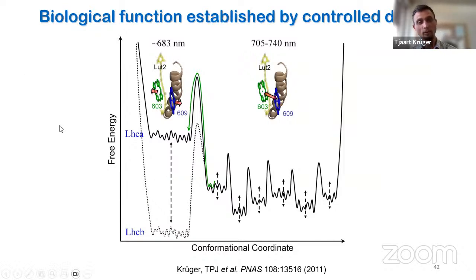So one can propose a generic protein structure, okay, where the equilibrium is slightly different between photosystem 1, in this case, where the equilibrium is shifted just slightly differently to put these two chlorophyll rings a bit closer together, whereas in the case of photosystem 2, the equilibrium is such that these two chlorophyll rings are on average a bit further apart. But both of them can switch to the other state by means of controlled disorder, and now the biological function is established by controlling this disorder.